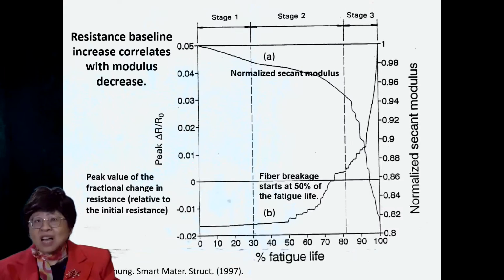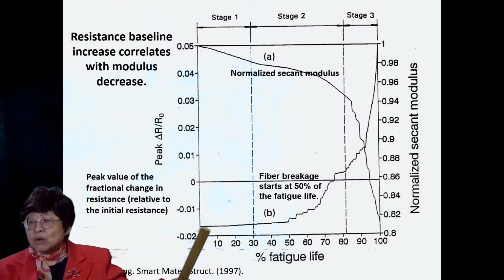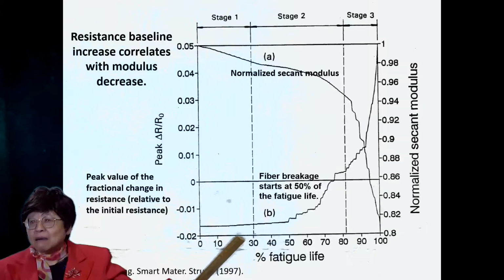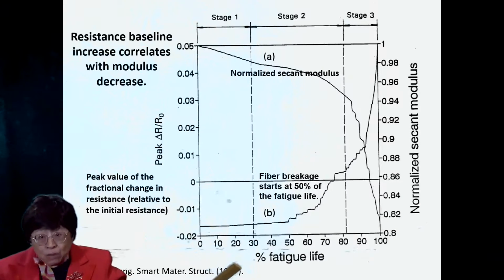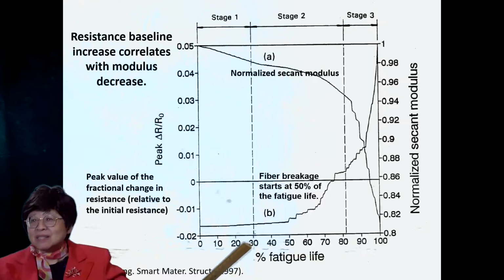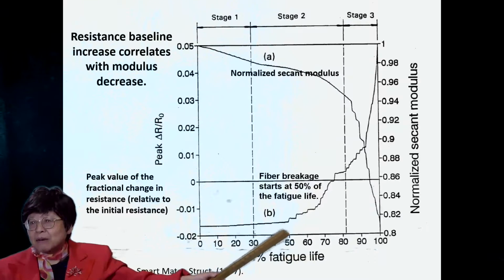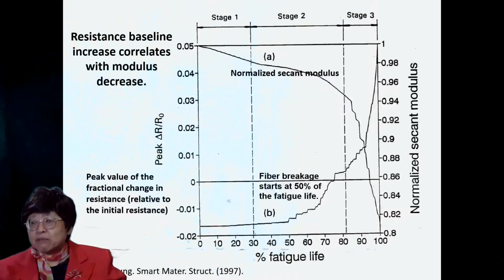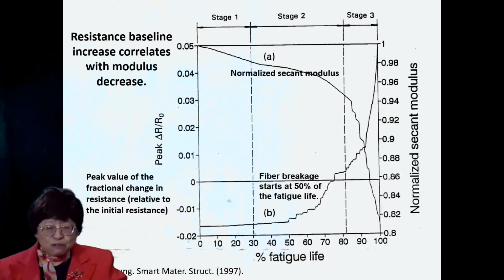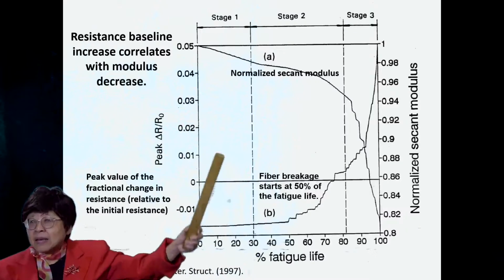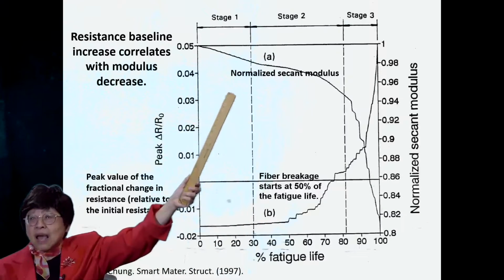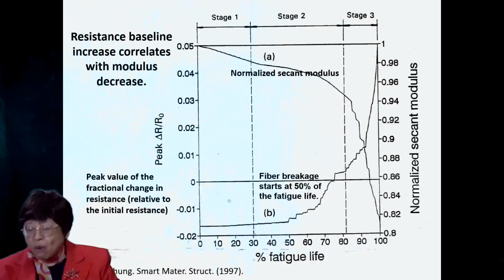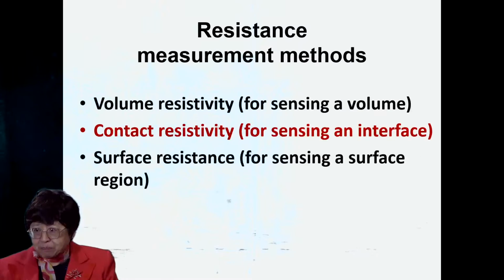So we can follow the entire fatigue life of the composite. Shown here, the bottom curve is the resistance, the peak resistance in every cycle. And we see that at about 50% of the fatigue life, the first spurt of resistance increase occurs, meaning that the fiber breakage starts to occur at about 50% of the fatigue life. And the upper curve is the modulus, and indeed the modulus goes down, supporting the fact that there is damage.